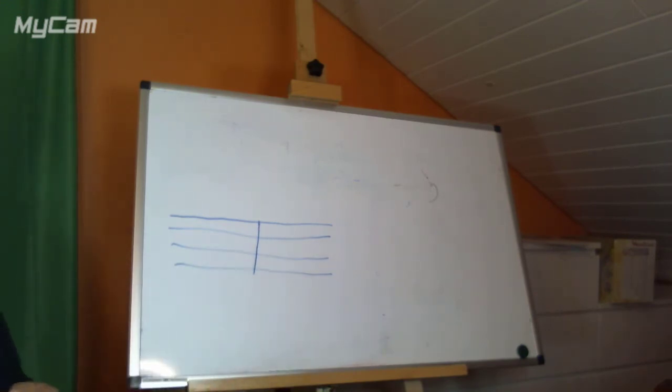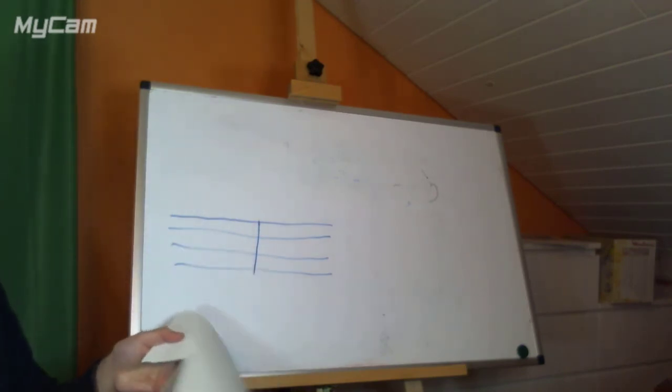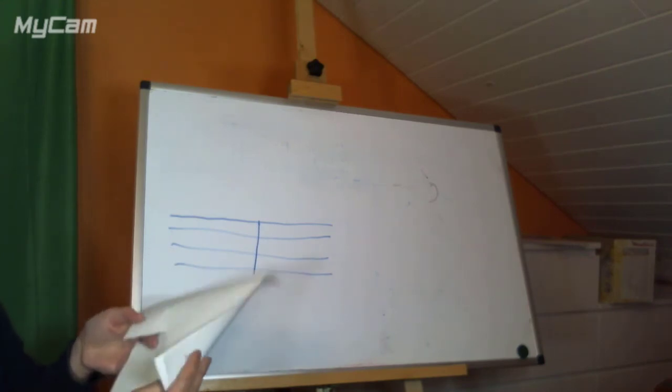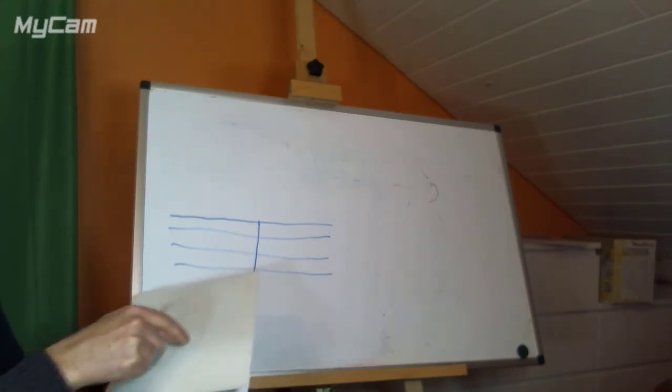The important thing about this defect is that it is a both directional low energy defect that avoids exactly the problem that we just covered. So the problem that we just covered is it's difficult to start an island. It costs more energy to start the next layer. But here, the layer will never be filled because we fill from the edge of our spiral. There's my spiral.